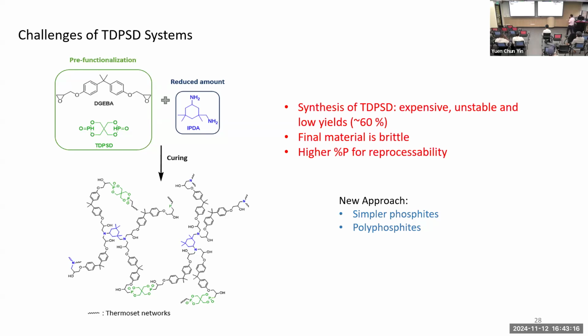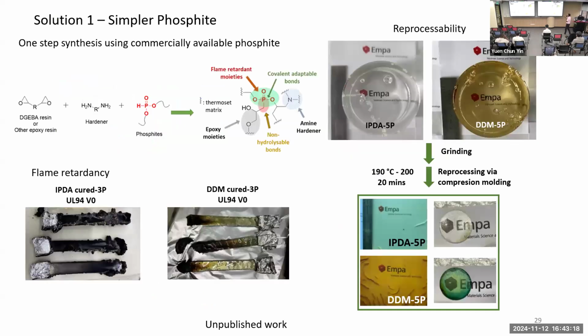But then we resolve this problem by developing simpler phosphites. I'm not going to go into the chemistry, but the end result is we are able to resolve this problem with a different idea. The monomer is difficult to make, but then you start with something else as a starting material, I would say. But you get the same results, I would say.